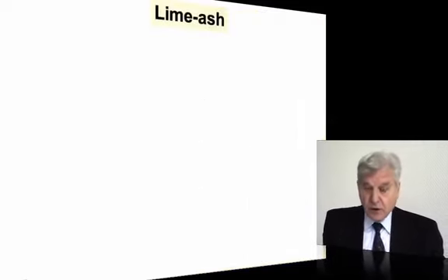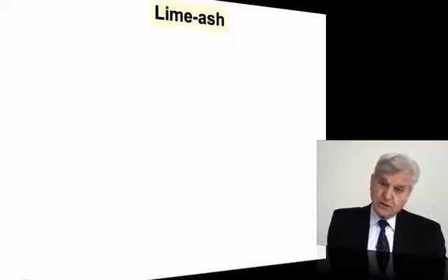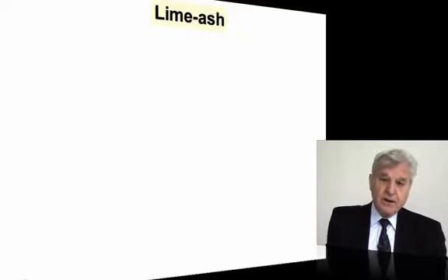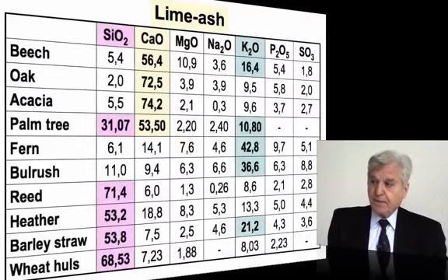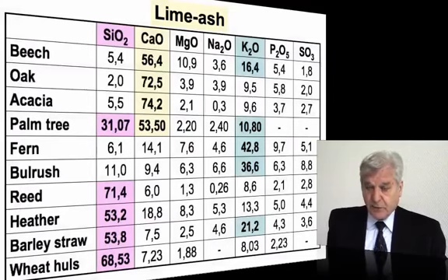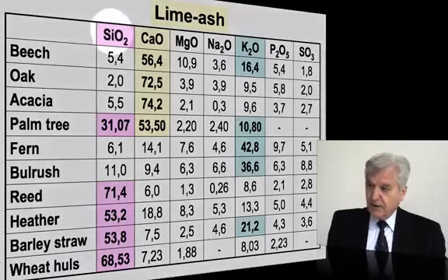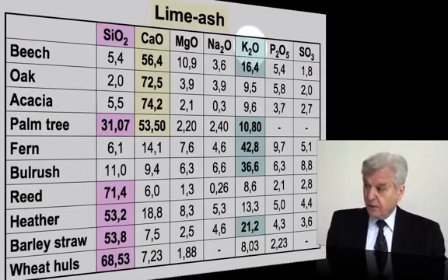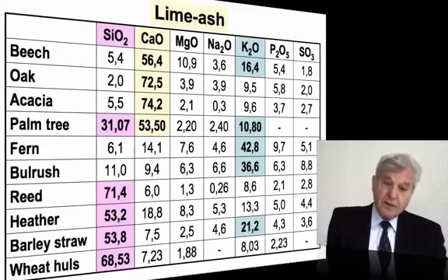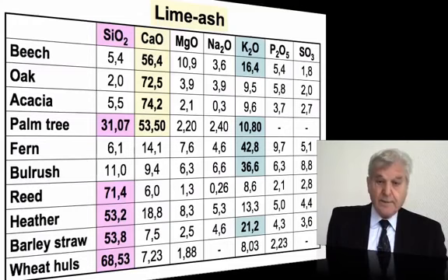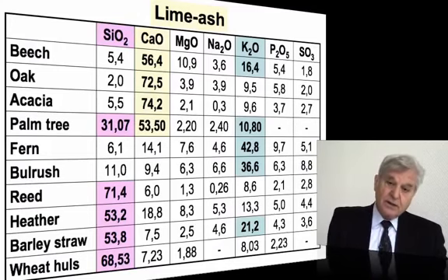And if we want to understand what was the reason, we have to come back to one essential knowledge, that is the one that plants were supplying a lot of chemicals during antiquity and even during our Middle Ages in Europe. If we look here at the ashes that are the results of the burning of wood or plants, you see that we get plenty of SiO2 that is chemically available for the reaction, plenty of CaO, calcium oxide in beech, oak, acacia, palm trees, plenty of alkali, K2O, in beech, in palm trees, in fern and bulrush and so forth, which means I am claiming that this is the way how they used the plants and the woods in the production of these ashes that have been the sources of the chemicals.